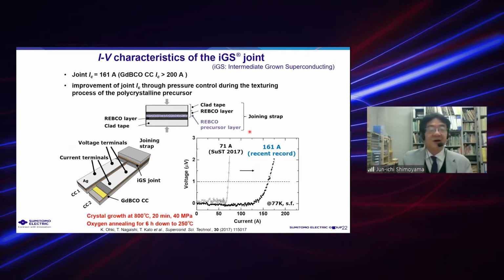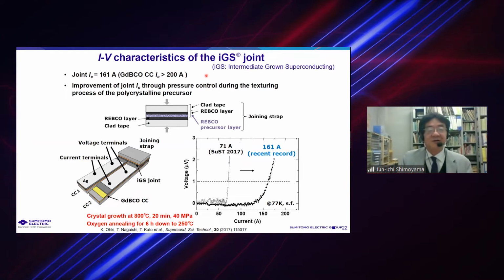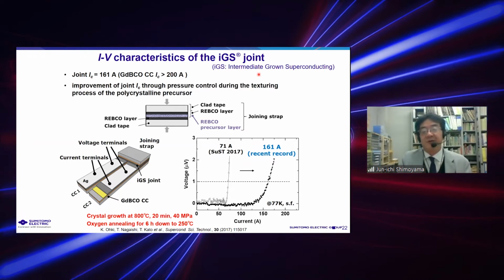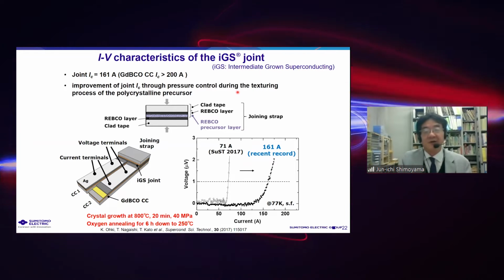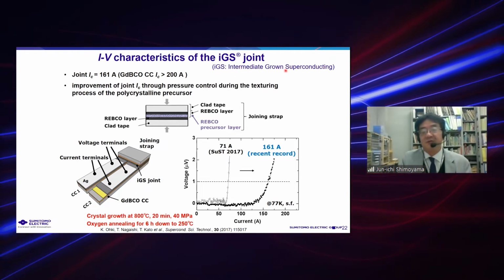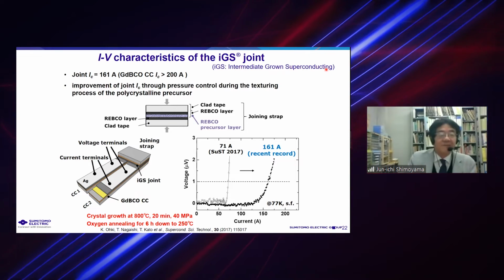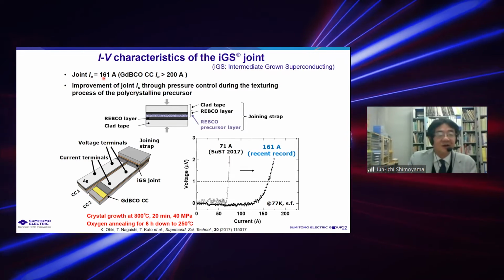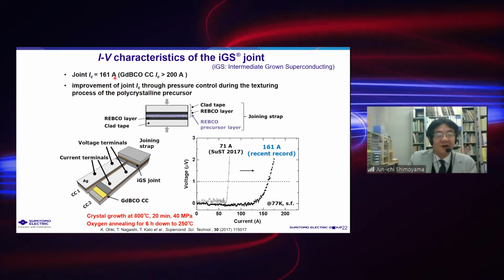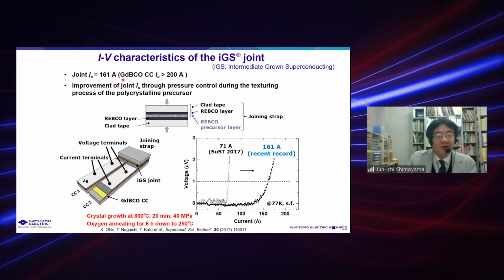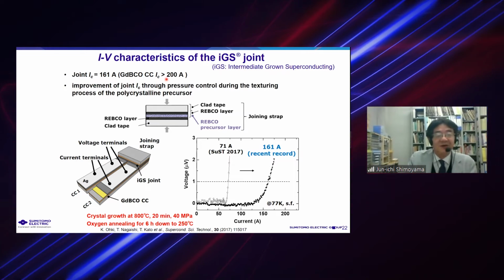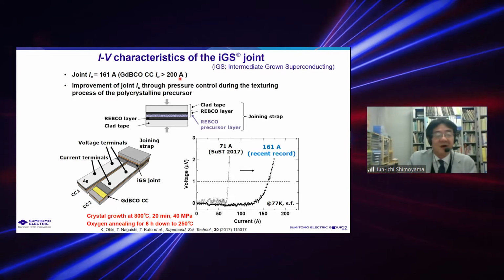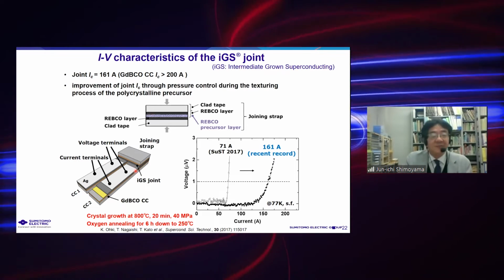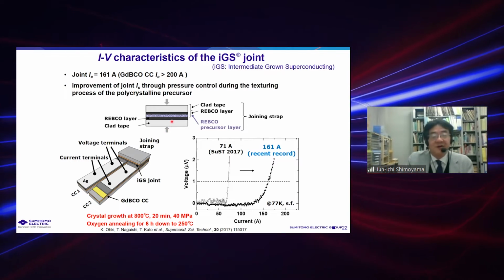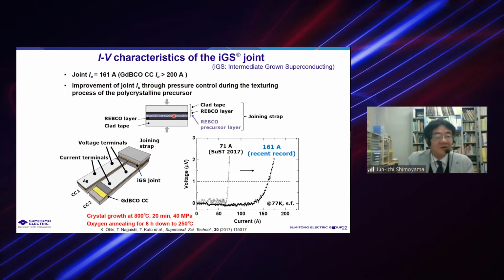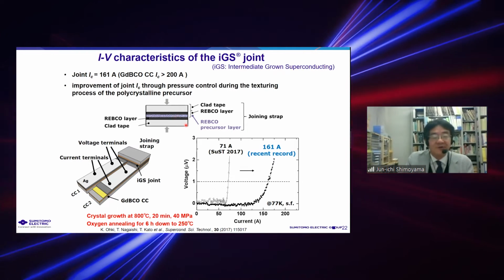So this idea was realized in the IGS joint developed by Sumitomo Electric. IGS means intermediate grown superconducting. The Ic of the joint is 161 amps at 77 Kelvin, while the coated conductor Ic is greater than 200 amps. In this method, they use intermediate layers as here. I will introduce this technique precisely.